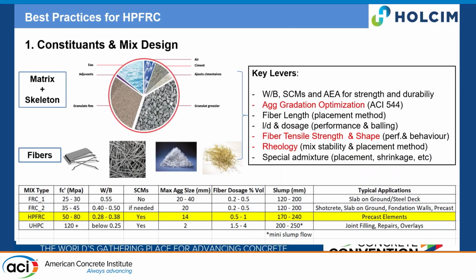So, quick review of the best practices to ensure how we can make mass production of fiber reinforced concrete, typically from the lab to the production. First, in terms of mix design and the key levers to maximize the synergies between the fibers and the matrix, the first step is to look at, based on the durability requirement and the exposure conditions, do we need SCMs? Do we need air entrainment? Do we need to play with the water cement ratio and the porosity of the matrix